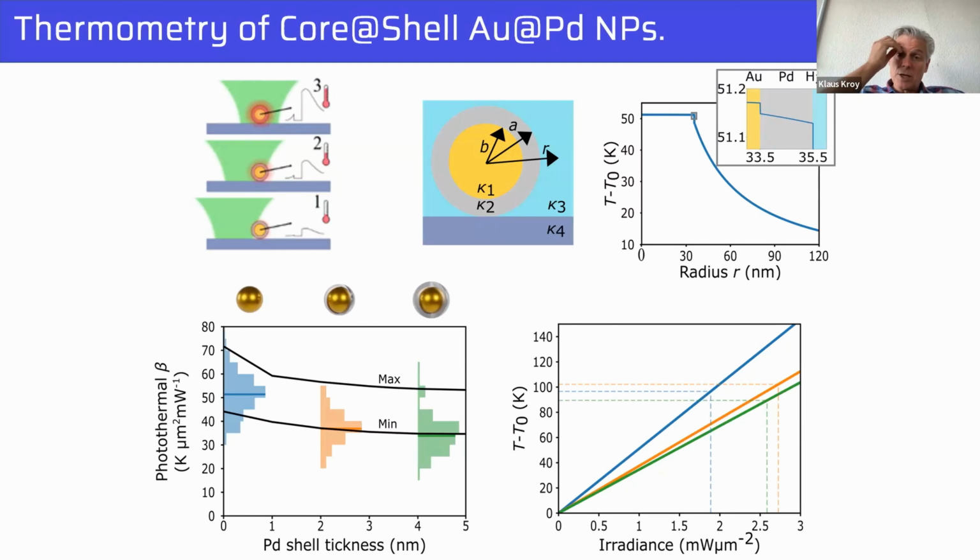Of course, in the simulation we have no radiation, we have only convection, or collision of particles that transport the temperature, and in the experiment it's even more complicated because some of the heat is transmitted with radiation and some of it is convectively or conductively transmitted. But what I also heard from people is that Kapitza resistances are normally small in most liquids. If you are not doing something really special with, I don't know, superconductivity or whatever, I think normally they are small and hard to measure.